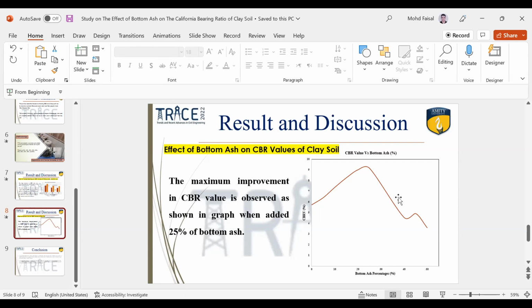No, up to 15, we didn't get any increase. Between 25 and 15, we didn't get any increase. But for the plain bottom ash, the CBR value increases. It's more than plain soil and 25% with the clay ash. Okay, thank you. Thank you.